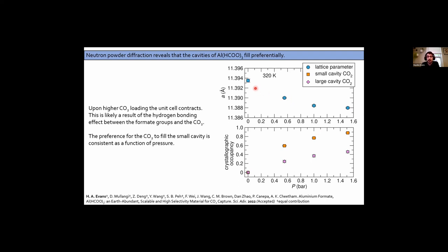And so from the crystallography, you can do this over different pressures, right? So as you dose CO2, as more and more CO2 goes into the compound, you get a lattice contraction. That's atypical to most MOFs or adsorbents, right? They usually expand as you fill it up. That's coming from the hydrogen bonding effects of the small cavity, right? Like it's sucking itself up or, you know, breathing in.